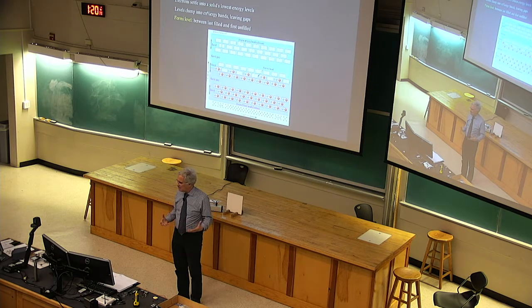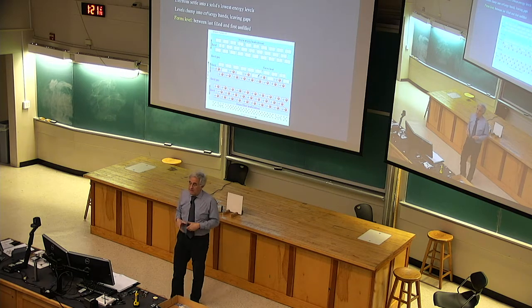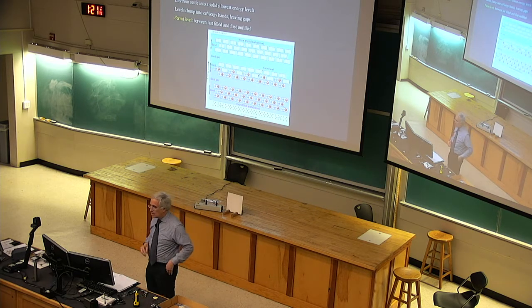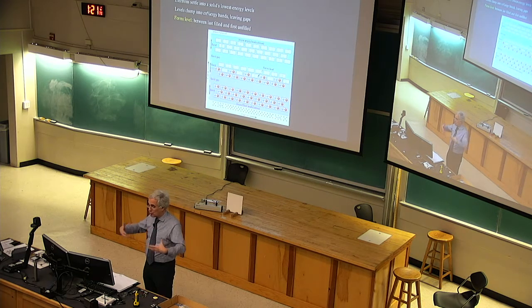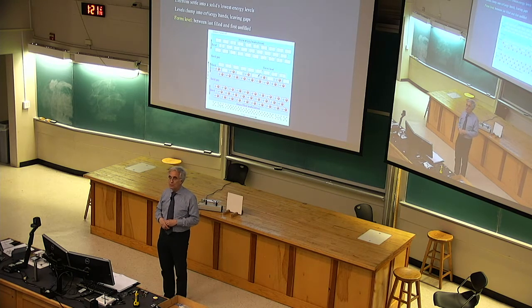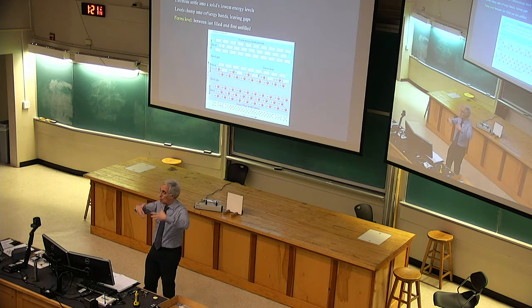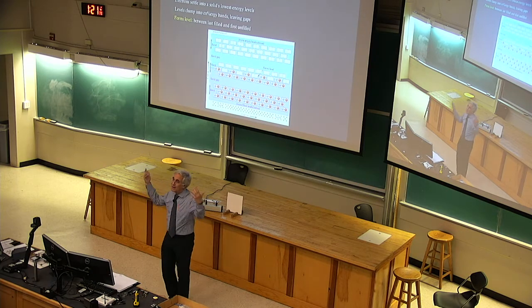Are there bands of orbitals? Well, they're shells of orbitals. It's a similar idea that the orbitals in a solid typically show up in bands that have similar character in the structure of the standing wave and also similar energies. So as you're building out the solid, putting electrons in, you fill bands of levels, and you start filling the next band of levels, then you start filling the next band of levels. They're all working their way up in energy, and eventually you run out of electrons.